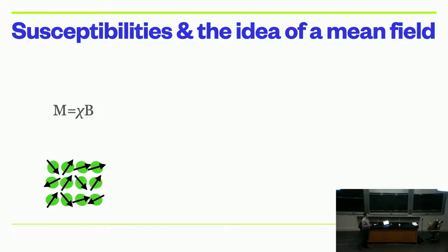So what's happening in the system? How do we characterize the response of a material that's near a ferromagnetic transition? And again, the magnetization is now our order parameter. That's the parameter characterizing whether we're going through this phase transition or not. And what we're looking at is its response to field. So field B is like you're applying a magnetic field to the system, and you're looking at how the response in the magnetization actually looks.